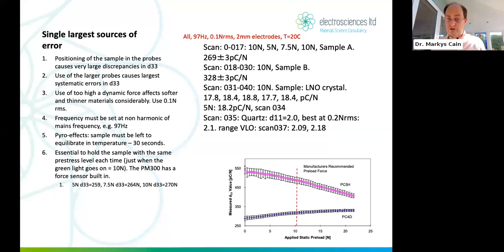And if you look at this graph on the bottom right, you can see real data, okay, for a soft material on the top and the hard piezo material on the bottom. And the y-axis is measured d33 value, and the x-axis is static preload in newtons. 10 newtons is the manufacturer's recommended preload. Now you can see that the hard material is not so dependent on preload. It is a bit, but it's not so dependent. But the soft material is much more dependent, very much more dependent, and even a few newtons difference can impact your measured value by a lot.